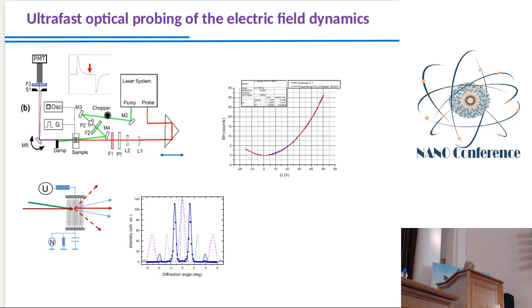And so, in fact, here is the dependence of the second harmonic generation efficiency on the applied electric field. You can see that at zero applied electric field, we have no second harmonic, but when we increase the electric field, this second harmonic intensity increases parabolically, and in fact then, from the second harmonic intensity, we can determine what the voltage was and what the electric field was inside our material. With this technique, we have ultra fast time resolution. This time resolution is limited only by the duration of the optical pulses, and so using a femtosecond laser we have femtosecond time resolution.